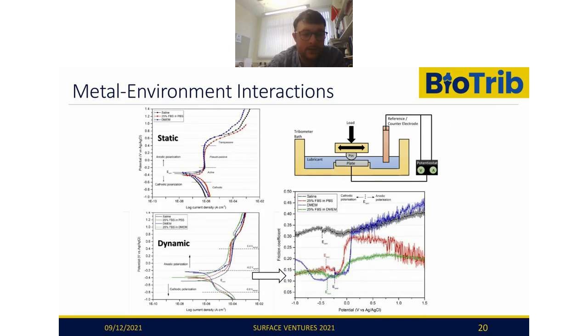And again, whilst these materials are affected by the lubricant that we use, they're also affected by the nature of the applied electrochemical potential. We can manipulate the friction response by quite simply changing the voltage that we apply between our tribocouple and the potentiostat. And we can ultimately see that these protein or organic containing solutions are very sensitive to this voltage that we apply. And so they indicate that they interact and are involved in these electrochemical processes, which are also interlinked with the tribology.